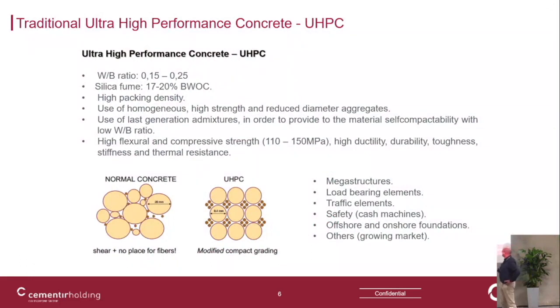The starting point is the philosophy of traditional ultra-high performance concrete, where we have some characteristics that are specified to make this high performance concrete. The water binder ratio for reaching a high level of performance is very low. We have products with a water binder ratio of about 0.17, 0.18. And most of the traditional UHPCs have silica fume, which is a very fine powder, with a content of about 17 to 20% by the weight of cement.